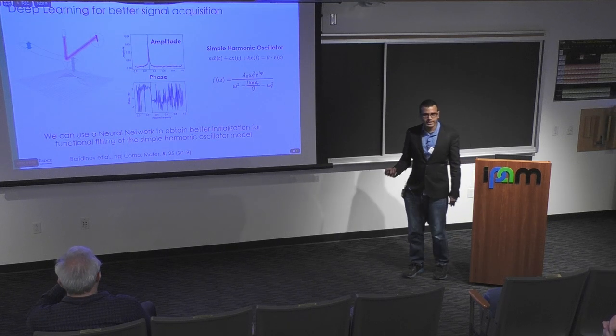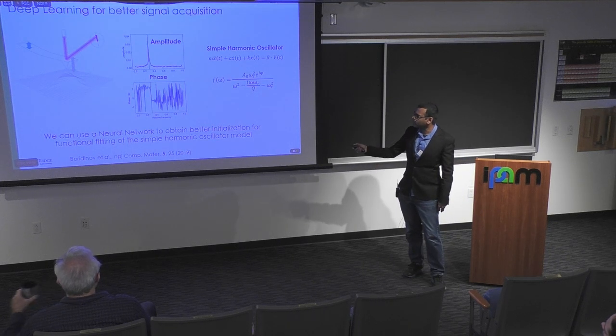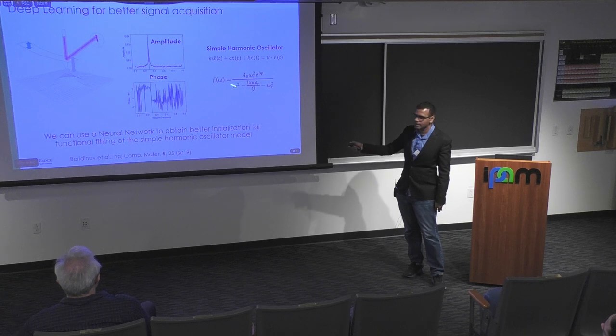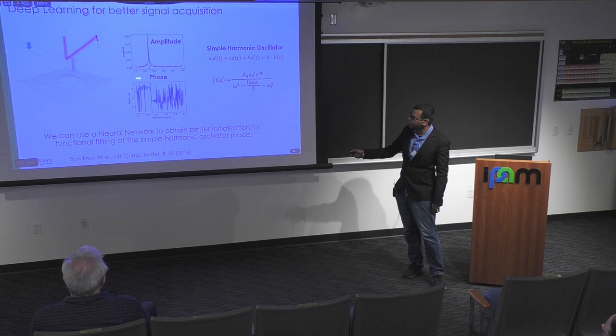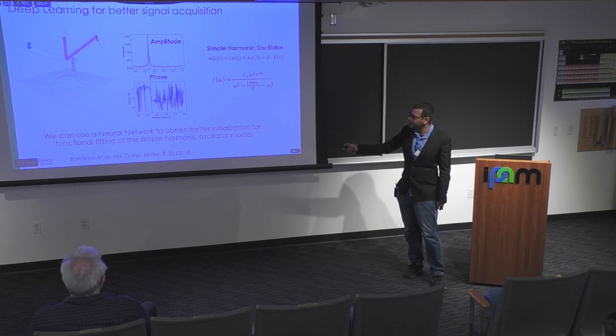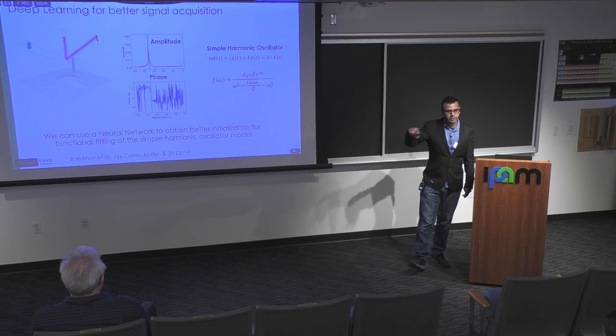Well, first we need good priors that we use for, let's say, an LM algorithm to be able to determine these parameters. But we typically don't have great priors if we have very noisy data. Like our prior or starting point might be to take the maximum point here as the starting point for the amplitude when you want to do this inversion, right? But this actually doesn't work very well when you have very noisy data sets. And so the first thing that we thought might be worthwhile in this case was maybe we can use deep learning to help us out here.